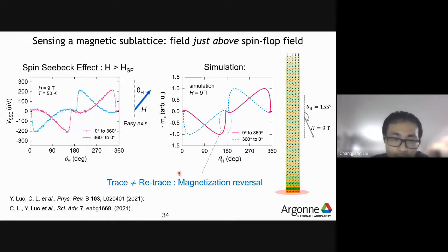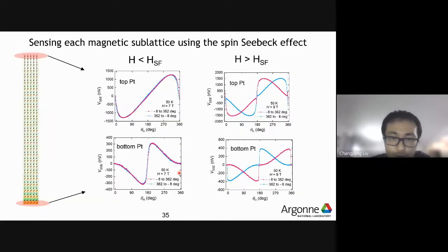So the first thing we have achieved is that this spin Seebeck effect can be used to characterize or measure the magnetic components of the sublattice very precisely. To show you further, we would like to measure the sublattice at the top surface of Cr2O3. As I mentioned earlier, the top surface, the top layer of the Cr2O3, corresponds to a different sublattice.